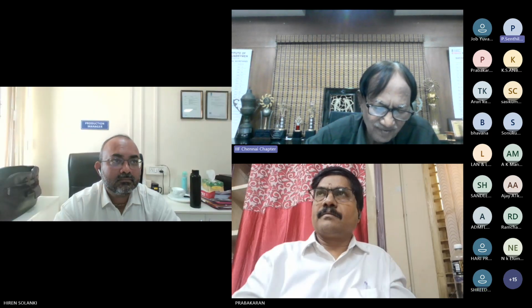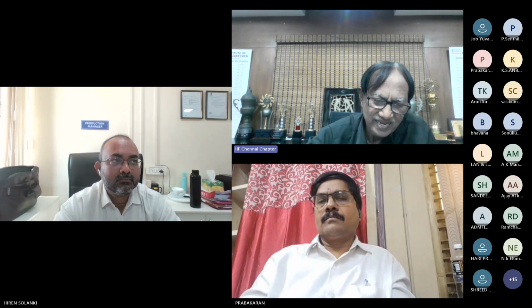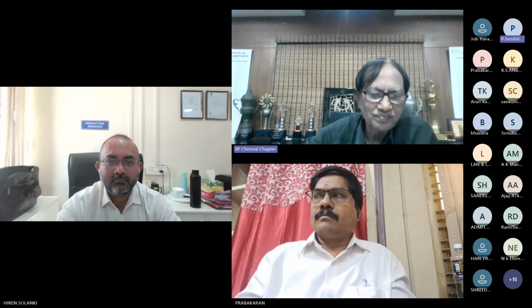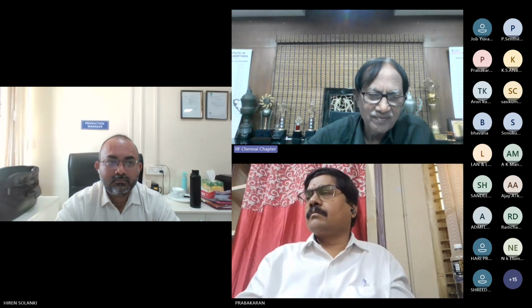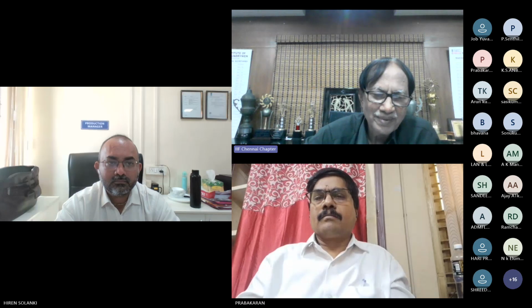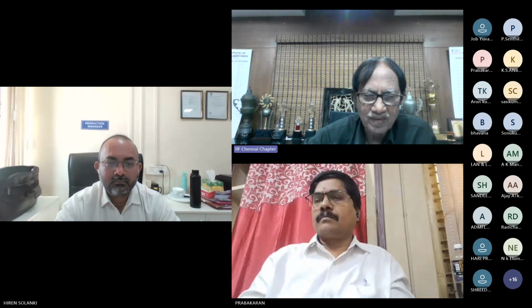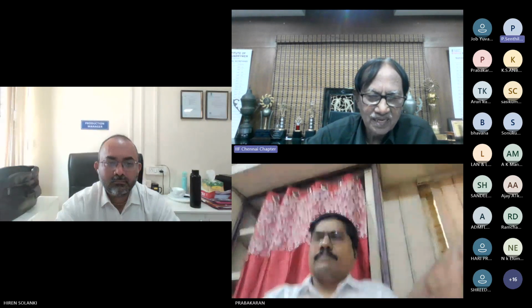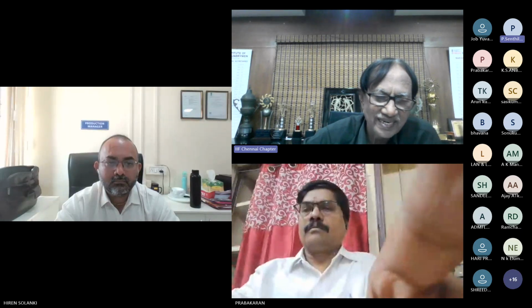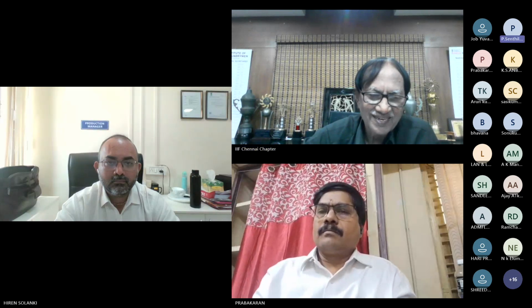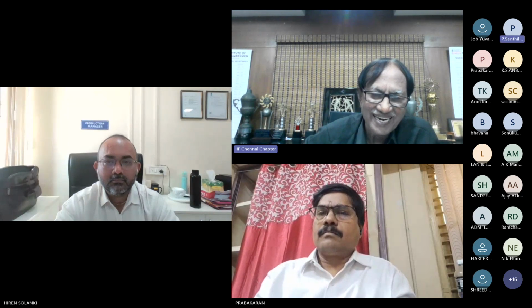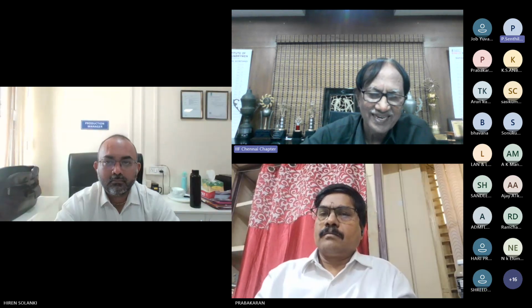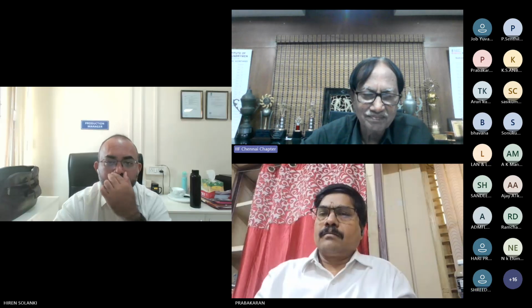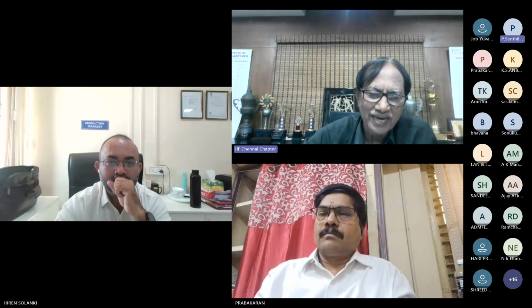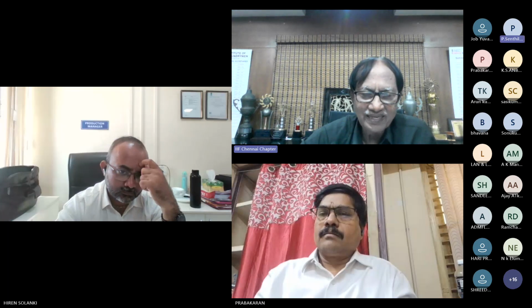Yes. Mold filling, as they say in the laboratory, we cannot do in the shop floor, so I have a thumb rule. You keep the molten metal filling time 12 seconds, plus or minus 2 seconds, not too low. You adjust the gate entry to this. If you keep a very long filling time like 20 or 30 seconds, the metal in the ladle will get cold, 100%. The operator has to hold it, or the autoladle has to remain hotter. So in my practical experience, I try to keep the filling time for any casting within 10 to 12 seconds, and then I adjust the pouring gauge.